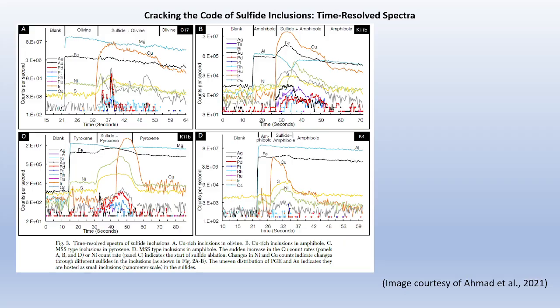Take panels A and B first. They both show copper-rich inclusions, one hosted in olivine and the other in amphibole, around 36 to 38 seconds. That's the moment the laser hit the sulfide droplet. But notice what else happens. Gold, palladium, and even silver spike at the same time. And that's direct evidence that these trace metals were tightly bound inside the sulfide phase. They're not hanging around in the silicate host.